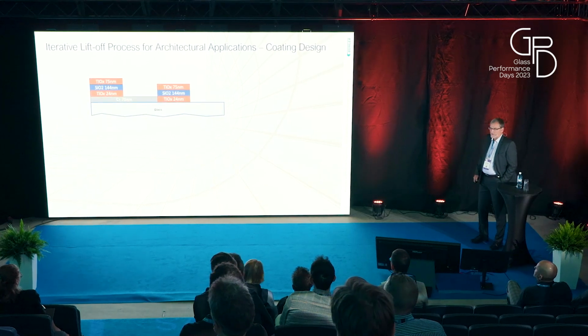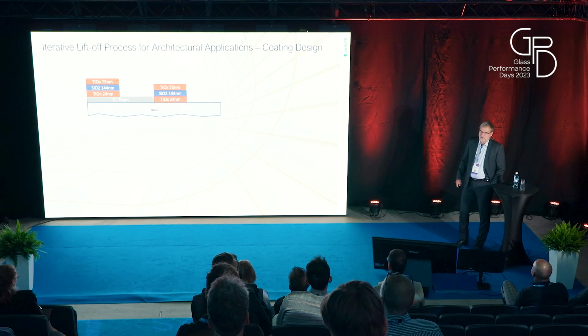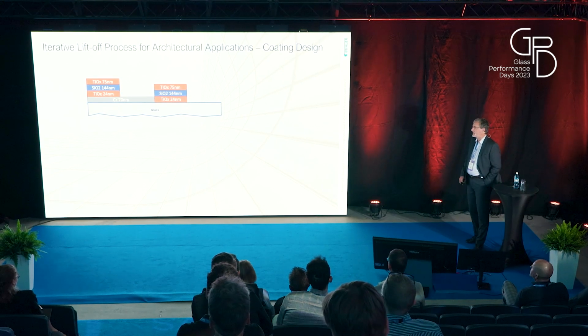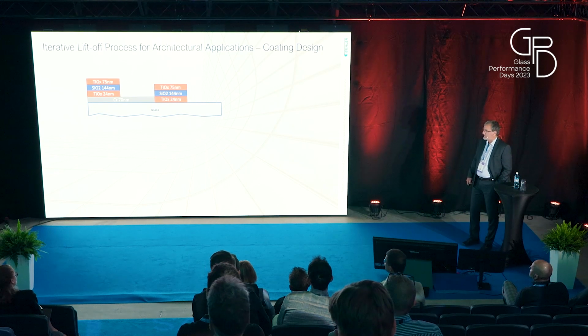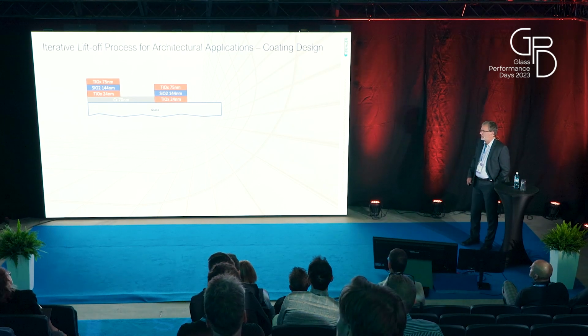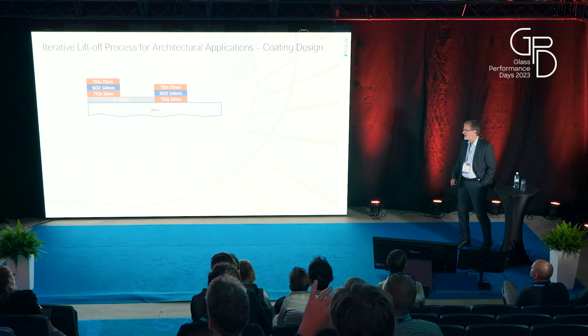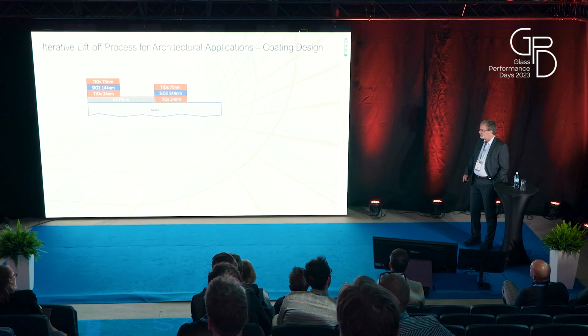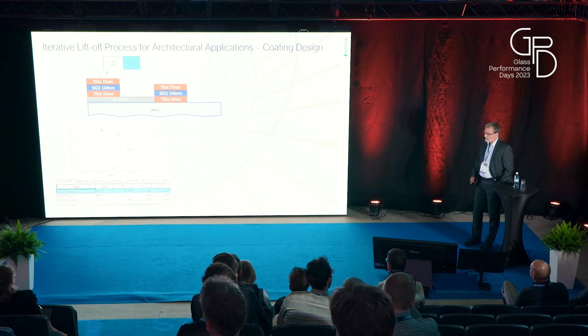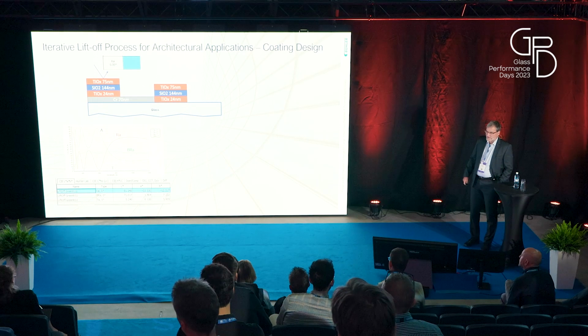Now we can think of how we designed it, and this was not a very extensive design work. We just wanted to minimize the dielectric layers and get some distinct colors we can observe. So we decided on a 3-layer coating, high, low, high, typical to get some colors and some spectral changes: TiOx as the high index material, a low index material, and high index again. This was what we were aiming for. So you see the spectra, but more important, the colors in the table below.